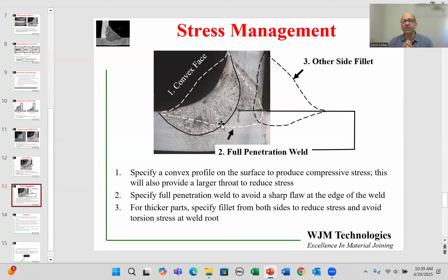Now this full penetration weld can be made if it's fairly thin, let's say less than say 3 millimeters or 1/8 of an inch or less. If the component is slightly thicker than that, then you may have to provide a V-groove on the front edge of the weld so that it allows the fusion to go all the way back. And that might require 1 or 2 passes, but you can make a profile which looks like this dashed white line. Now, sometimes the component is much thicker, and in that case, you may have to go from both sides.